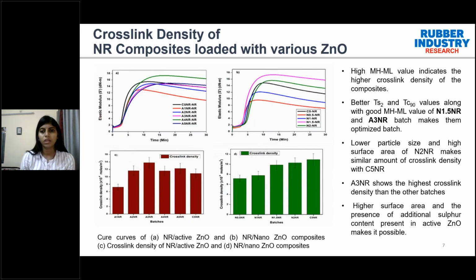The compounds with the optimum cure time, TC90, and the processing safety, scorch time TS2, were the N1.5 NR and A3 NR batches. That is, the compounds with 1.5 phr of nano zinc oxide and 3 phr of active zinc oxide gave optimized properties among all the batches. This could be due to the lower particle size and high surface area of the nano zinc oxide, which was able to give a similar amount of cross-link density compared to the 5 phr conventional zinc oxide loaded compounds. A3NR shows the highest cross-link density of all the batches. This could be due to the higher surface area and the high number of reactive sites in A3NR, along with the extra sulfur content present in the active zinc oxide, making this possible.